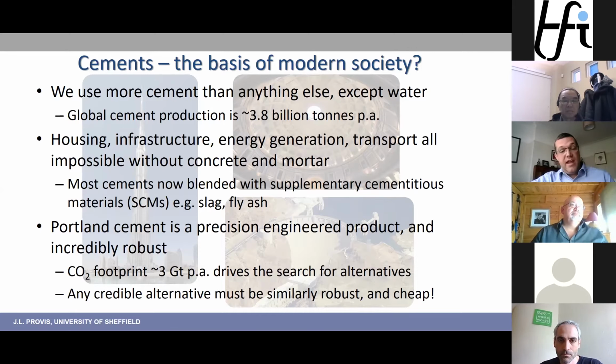Fly ash, the ash captured from the chimneys of coal-fired power stations, again, incredibly valuable, is blended in as a supplementary cementitious material. The cement sector overall is a net consumer of solid wastes to a very, very large degree. There's gaseous waste emissions, and I'll come back to that. But as a part of a circular economy, cement production is consuming, and concrete production even more so, these very high volume waste materials from other industries. Actually, we run into problems sometimes because we start to run out of other people's garbage. We start to run out of supplementary cementitious materials in certain forms in certain parts of the world. We need to find alternatives. And that's a challenge for the sector moving forward, how we can actually meet our materials needs.